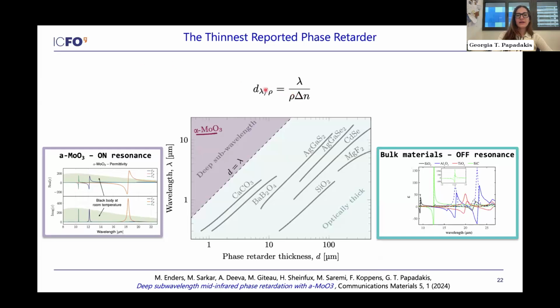So here we did a calculation of the thickness of a half-wave plate made out of conventional materials and molybdenum trioxide. So for these conventional materials, you see that, first of all, you are in the very thick wave plate regime. So these are optically thick materials that are tens of wavelengths, if not thicker. In addition, these curves actually terminate, and when they terminate, it's when you actually have an absorption peak, so the material cannot be used anymore because it's not transparent.